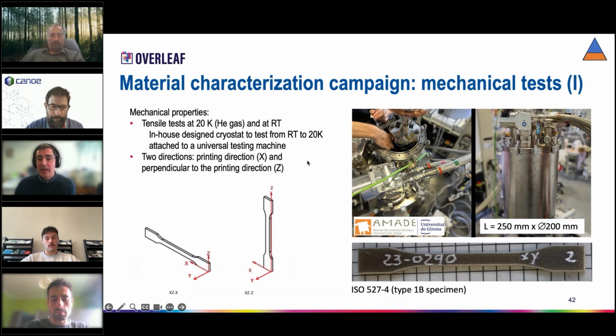In this case, the specimens tested were dog bone specimens. We follow this standard, so thanks to the dimensions of the cryostat, we could test the standard specimens. And as Ander commented, we have tested two different directions. One is specimens printed in the printing direction, and another set of specimens perpendicular to the printing direction, to know the properties in both directions. There is a third direction, the Y direction, but in that case it was considered that it had the same properties as the Z, which is perpendicular to the printing direction.